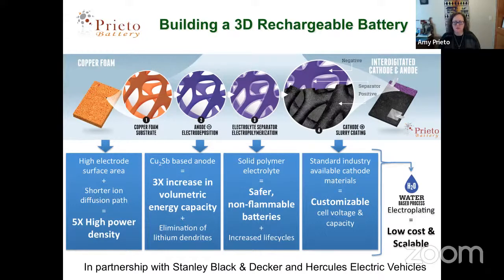So I knew that it could be used to coat structures with very high fidelity, but also it's a really good tool for making materials. And so the way that we start is with copper foam as our current collector. Copper is the common current collector in a lithium-ion battery for the anode anyway. And in this case, the surface area to volume ratio sets the ultimate top limit for the power density of the battery. We're going to use that copper foam as the working electrode to deposit our anodes.